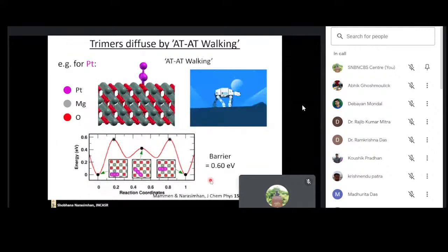It is neither the cartwheeling nor the hopping. And I don't know how many of you have seen the Star Wars movies, but in the Star Wars movie, there are these transports called AT-AT walkers. And this sort of slow, ponderous diffusion of this trimer reminded me of the AT-AT walkers in Star Wars. And so I called it AT-AT walking. And this is the profile for that process. And this is the barrier of 0.6 electron volts.